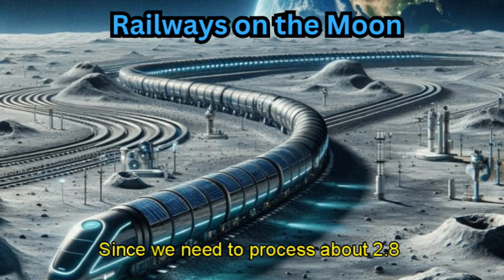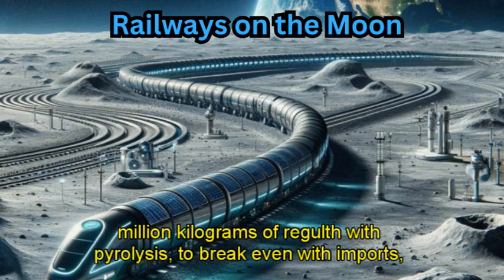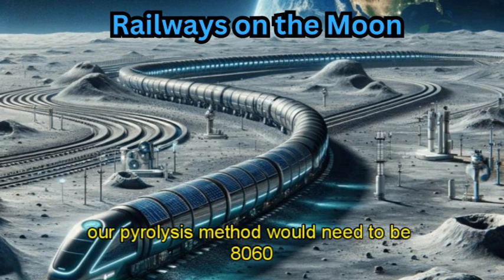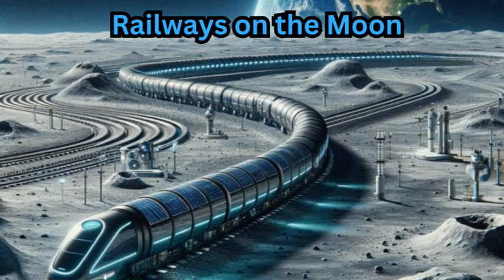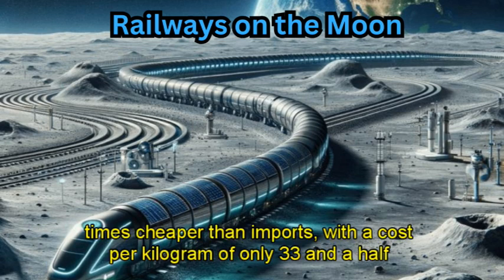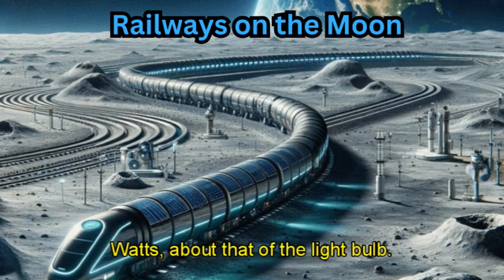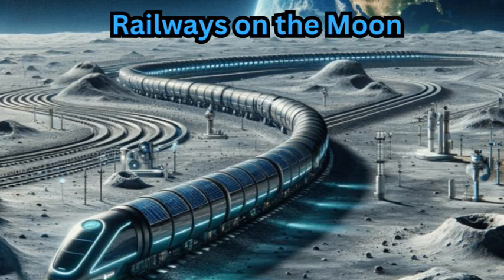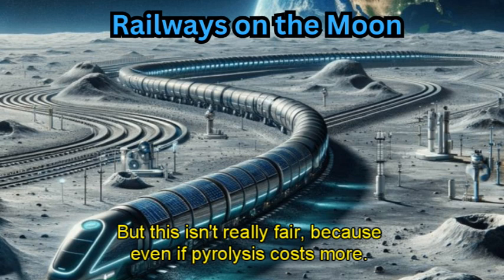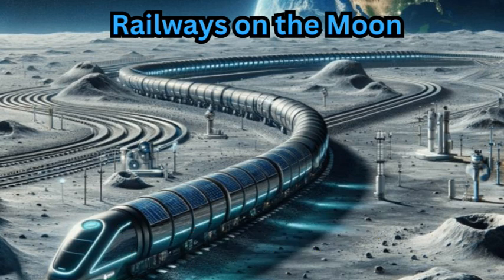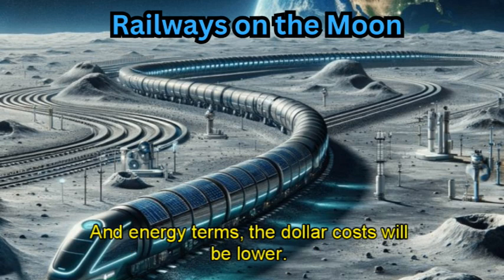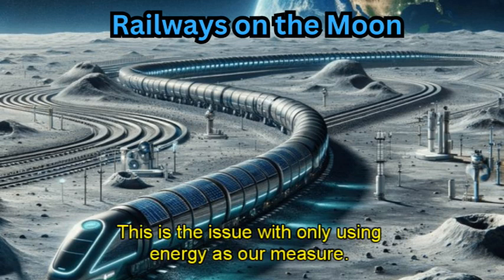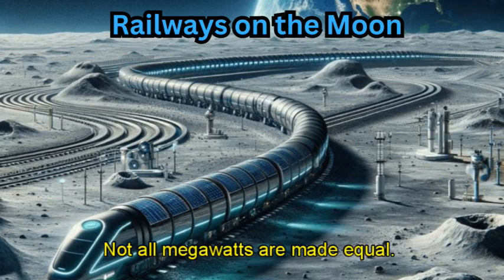Since we need to process about 2.8 million kilograms of regolith with pyrolysis, to break even with imports, our pyrolysis method would need to be 8,060 times cheaper than imports, with a cost per kilogram of only 33.5 watts, about that of a light bulb. But this isn't really fair, because even if pyrolysis costs more in energy terms, the dollar costs will be lower. This is the issue with only using energy as our measure. Not all megawatts are made equal.